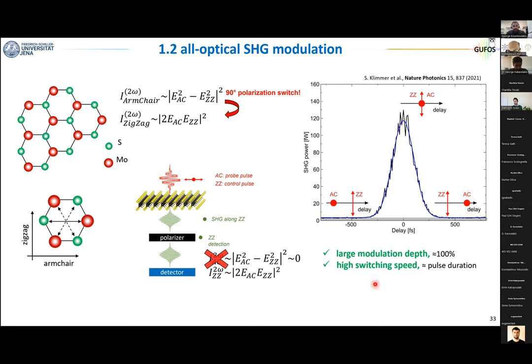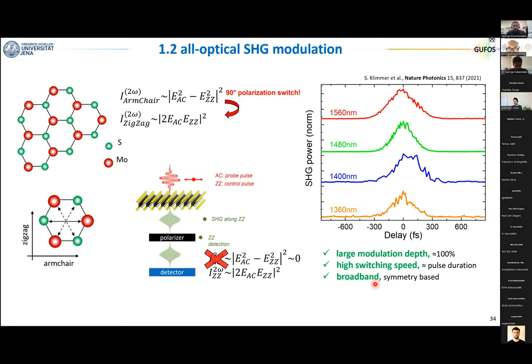So with this very simple approach, we get the largest possible modulation depth, really 100%. The highest possible switching speed, because this time we are not limited by the dynamics of the excited state, but only by the pulse duration. But we also get the largest possible bandwidth, because now you can do this for any wavelength that you want, and you don't need it to be resonant. And now, if you want, this approach is somehow the equivalent of a half-wave plate. So this TMD is a very efficient nonlinear and ultra-fast half-wave plate where you can rotate the polarization by 90 degrees on a time scale limited by the pulse duration.